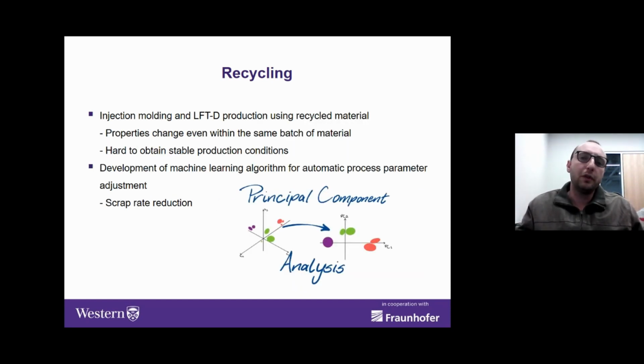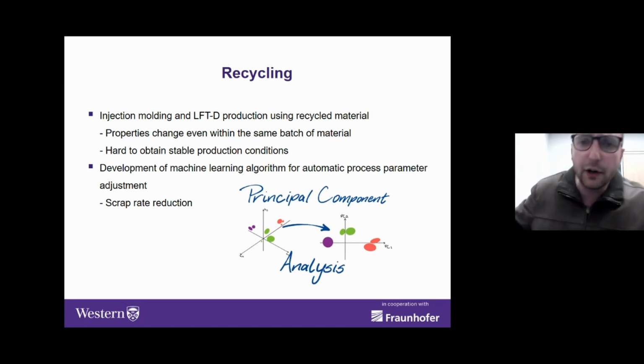Another interesting process for recycling is injection molding and LFTD. There is a lot of recycling done for thermoplastic materials, and those can be used in injection molding and in the LFTD line. The problem is that even in a normal material, there is a difference in the same batch between different granules, because they cannot all be the same. Now imagine in recycled materials, those differences within the same batch are quite big.